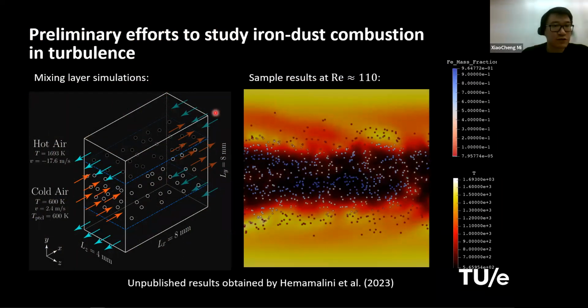So we are now starting doing some gas phase or carrier phase DNS to resolve the particle interaction with a turbulent flow. And in this case, it's actually not turbulent yet, because to resolve higher Reynolds number, it requires a higher computational cost. But you can see even for this very low Reynolds number flow, the particle energy release can trigger some turbulence or turbulent-like flows. That actually supports our hypothesis before, that the particle spacing can happen in a region where this interparticle gradient can produce kinetic energy of turbulence, right? And the further studies or more extensive results from this simulation will be presented later this year at different conferences.